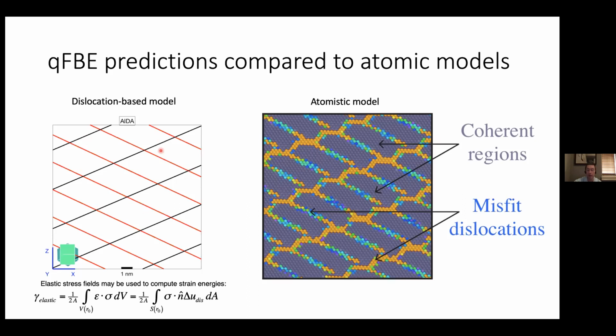So on the left, I'm showing you an analytical prediction of the misfit dislocation configurations at this specific interface on the right. You can compare the analytical prediction on the left to the atomistic simulation on the right, and they match really well. Now, because these lines in this model are nothing other than dislocations, and dislocations are very, very well studied and understood, you can calculate in detail, analytically, the stress and strain fields surrounding these dislocations. And from that, you can figure out the stress and strain fields surrounding the interface. If the interface is just made up of a bunch of dislocations, and you know how the dislocations behave, then you can figure out the stress and strain fields around the interface.